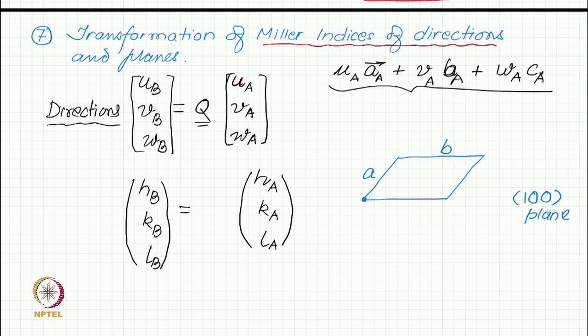One on the x axis, so it will cut the x axis here at A. 0 means infinite on the B axis, so it is parallel to the B axis. The plane should do something like this, and parallel to the C axis, so it is perpendicular to the plane of the paper. So, it is a plane like a prism face, it is standing on the plane of the paper perpendicular and is cutting the A axis at 1. This is what is the 1 0 0 plane.